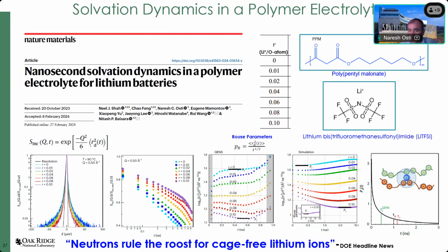And now we collected the quasi-elastic signal. As you can see here, those are the quasi-elastic signal as a function of the salt concentration. The width is going down as you go to higher concentration, indicating that salt has significantly reduced the dynamics of the polymer at higher concentration.